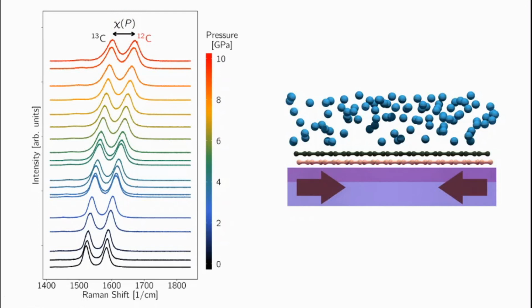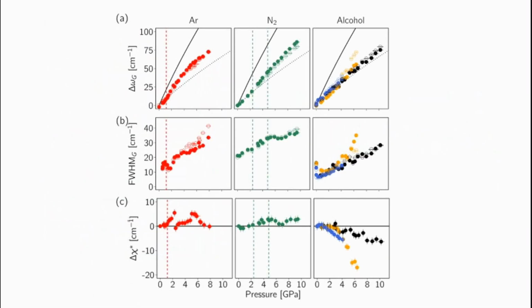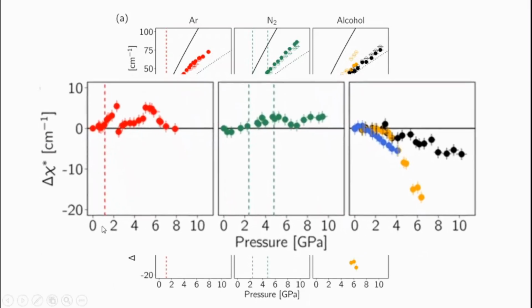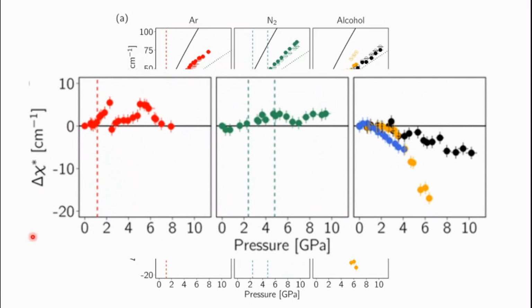We have followed the evolution of the G-band for the bilayer system in three different pressure transmitting media: argon, nitrogen, and a mixture of methanol and ethanol alcohols. Here we show the evolution with pressure of the position of the G-band, its full width at half maximum, and the difference in position of the two peaks, chi. All this is discussed in detail in the manuscript, as well as the evolution of other Raman peaks as the 2D band. Here we will only discuss the evolution of the chi parameter with pressure.